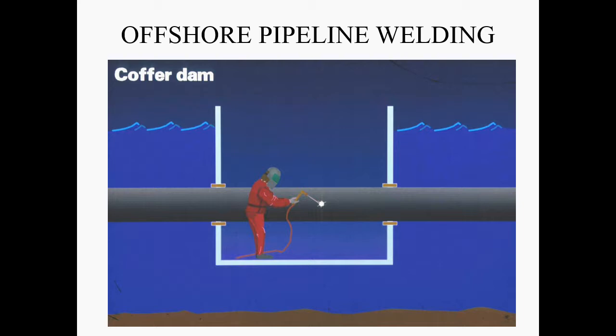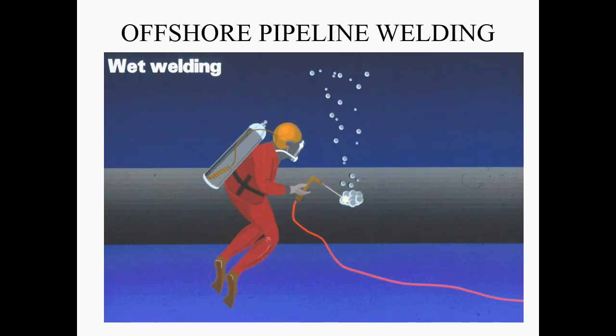This is the coffer dam. So remember, we are in the splash zone. This is the level of the sea. The welder gets into this box, which is fitted around the pipe. It carries out all the required welds. And basically the weld is carried out as a dry weld, as on land, because there is no water in there. The other case, the wet welding, is exactly like that. So it's in direct contact with the water.